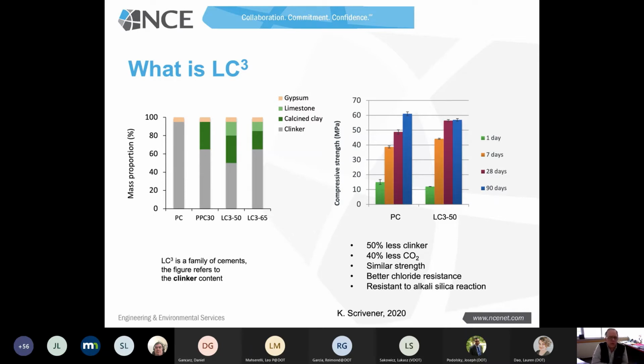LC3 is a relatively new technology. It's been developed. It's been used actually for paving in India. It's been used in a number of different construction applications around the world. It has not really made its way to North America yet, but it very slowly is. And you can get up to a 50% reduction in clinker by using an LC3 cement. So basically, we're going to take our CO2 emissions and divide it in half, roughly speaking. It's closer to 40%.